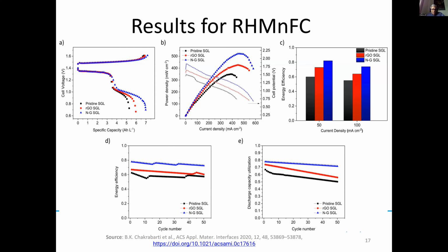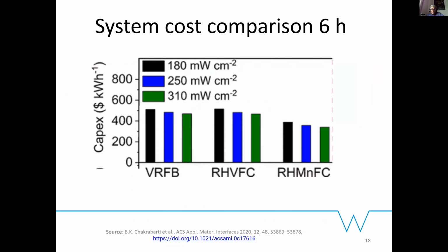The next thing is just a quick comparison of the costing, a very simplified costing model. So if we have systems like the standard vanadium flow battery, which is the commercialized system, being used for storing electricity for 6 hours, the costing at 3 different current densities shows that the higher the current density is, the costing goes down.